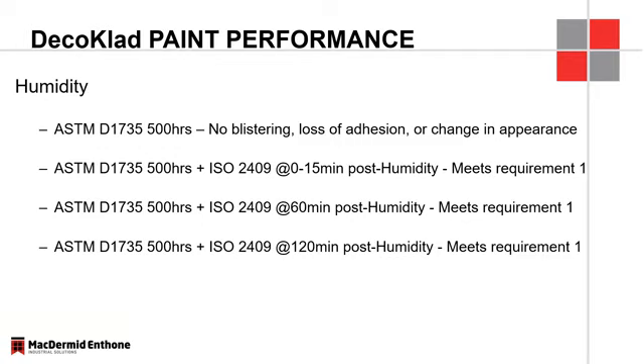Humidity, so to ASTM D1735, 500 hours in that test, showing no loss of adhesion and no blistering, and then followed by ISO 2409 and post-humidity testing. So, you know, tape tested at different time segments, post-humidity testing, and still not showing any signs of adhesion loss or blistering.